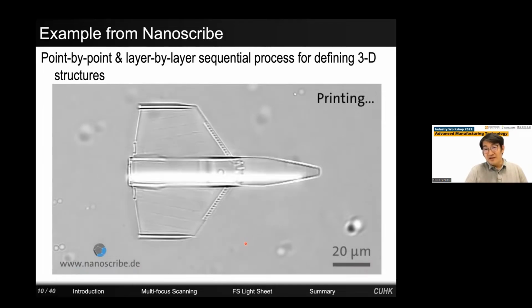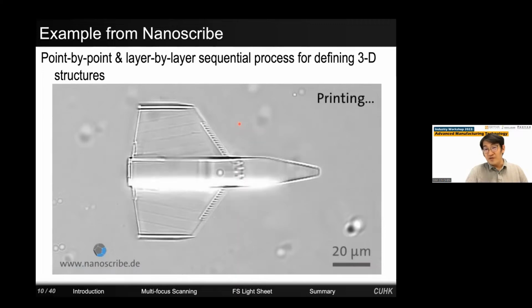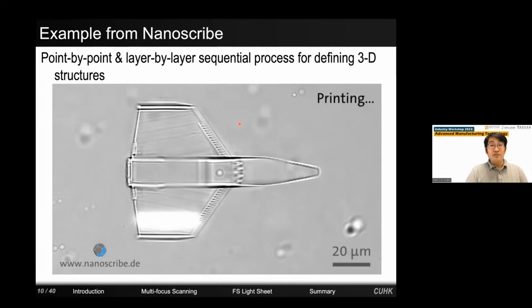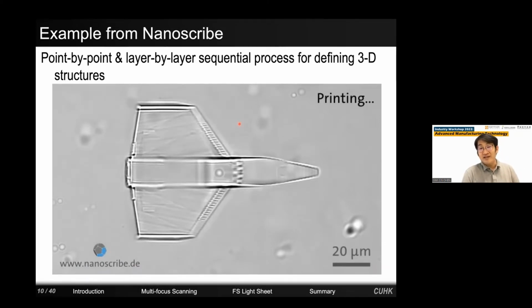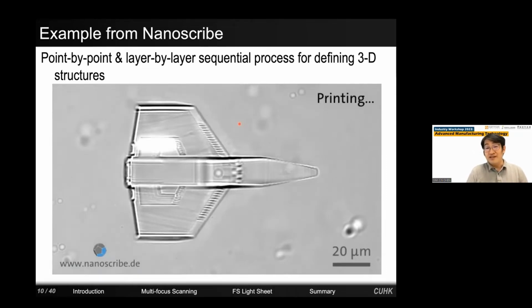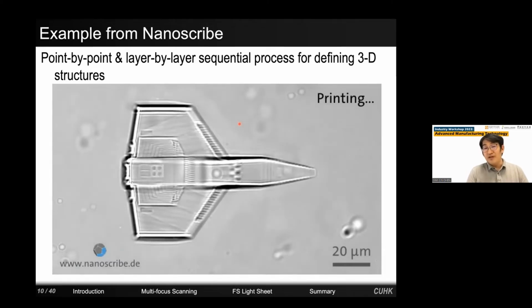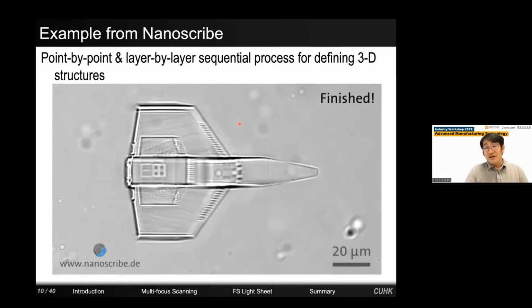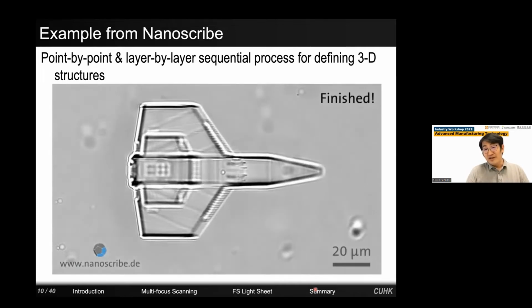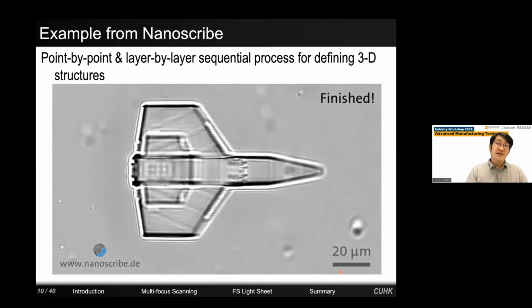And let me talk about more of the process. During the printing process, the objective lens is immersed in the photoresin, which is in liquid form and has a refractive index of 1.5. So in order to ensure high resolution, a matching index objective lens is used. It's typically an oil immersion lens. After fabrication, you take out the sample and develop it, and you can visualize the result in a high resolution electron microscope, as shown here just now.